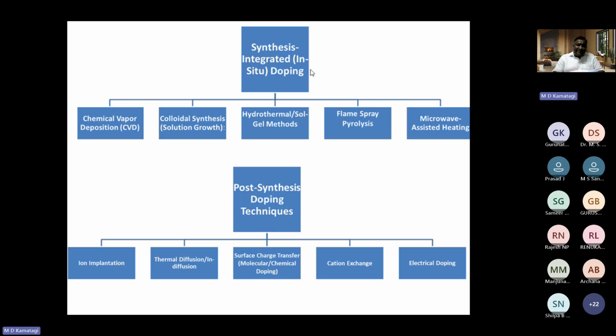In the case of thermal diffusion, the nanomaterial is heated in an atmosphere containing the dopant atoms, which then diffuse into the lattice. This can be combined with spin-on dopant techniques, where the dopant-containing liquid film is applied to the surface before heat treatment. There is also the surface charge method, which involves chemisorption or physisorption of organic molecules or metal particles onto the surface of the nanomaterials.